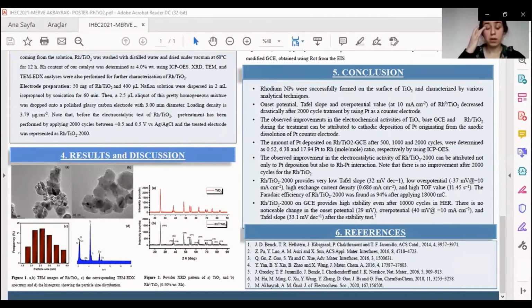Also, transmission electron microscopy EDX analysis given in figure 1D confirms the presence of the rhodium nanoparticles on the surface of the titania. However, due to the 0.5% weight rhodium loading, there is no peak indicating the rhodium nanoparticles in the X-ray diffraction spectra in figure 2B. According to the X-ray diffraction results of titania and rhodium titania, there is no change in the crystal structure of titania after rhodium impregnation.